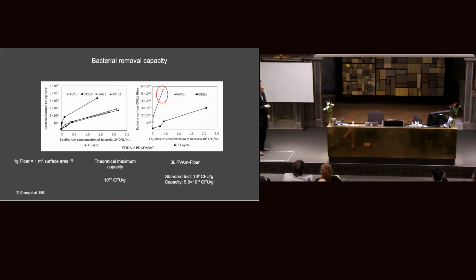Therefore, it's also important to know the capacity of the surface to absorb bacteria. One gram of fiber equals around 1 square meter of surface area. If we assume E. coli densely packs on the fiber surface and forms a monolayer, the theoretical maximum capacity would be 10^12 cell units per gram of fiber.